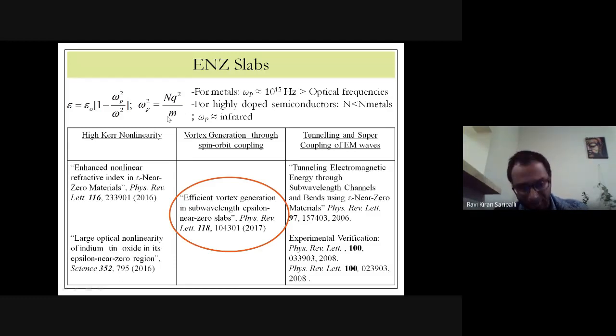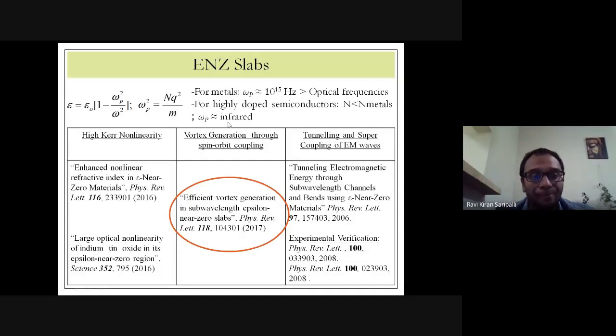For metals, this plasmon frequency lies at a value greater than optical frequencies. But for highly doped semiconductors, with material science emerging so much, you are able to produce these highly doped semiconductors, for example, indium tin oxide or zinc oxide kind of doped semiconductors. Then you start seeing that this omega p, or the plasmon frequency, comes into the infrared, and these are wavelengths that we can access in the lab.